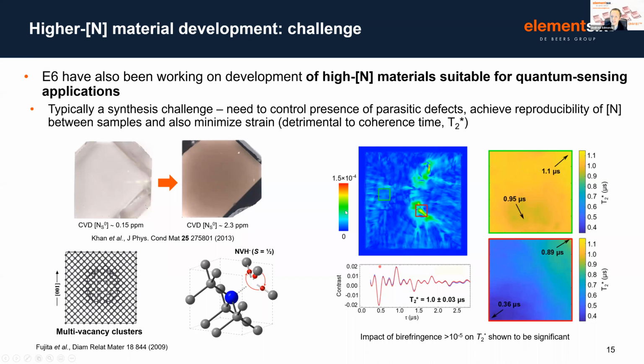So this is an example of what we see if we don't control strain in this sort of grade of material. What I show here is an optical birefringence image in the first instance, where we can see regions of high and low birefringence, which is a proxy to the strain in the material. Now, what we've done with our collaborators at Harvard is then map out what the coherence time is in different regions of this sample, and we can erode the coherence time very easily by a factor of 3. So this will have a majorly detrimental effect on the performance and sensitivity of this sort of piece of diamond for sensing applications. And in this particular example, the rough rule of thumb that we see is that birefringence in excess of 10 to the minus 5 has a significant effect on that coherence time T2 star in this particular type of material.